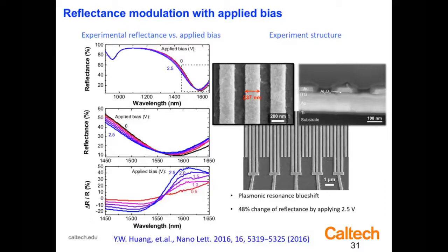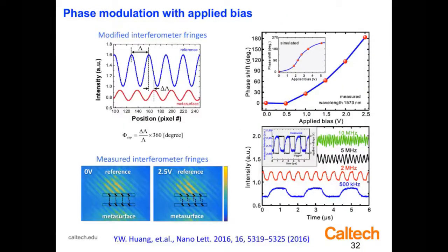But the important thing is that we can also modulate the phase. And this is a measurement. We actually use a fringe shift measurement in a Michelson interferometer setup to measure the phase. And we can see as we apply a voltage to our little transistor-like structure, we're adjusting the phase by about pi. If we could modulate all the way to 2 pi, we could access any phase state that would be needed to reconstruct a hologram. And so that's our goal. In other devices I won't tell you about, we've been able to get up to about 3/2 pi or a little bit further, not quite to 2 pi. But this is a transistor-like structure. We've actually run these up now to 100 megahertz.